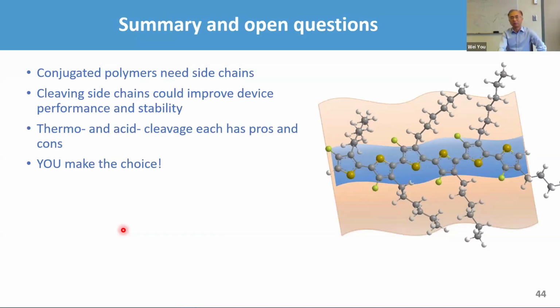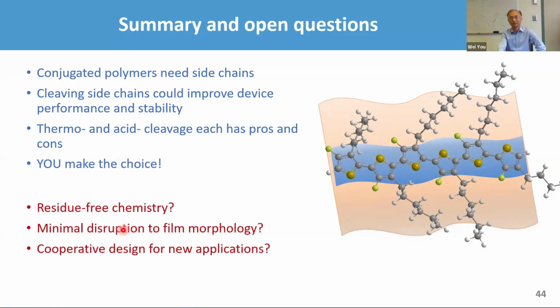So in summary, I hope at this point you understand why conjugated polymer needs side chains. We cannot get rid of that if you want to have the processing. So cleaving side chain will give you improved device performance and stability, right? Because you're being able to increase the Tg, the naked conjugated polymer actually has a very high Tg. So thermal and acid cleavage, each has pros and cons, as well as base and photo, all these things. You make the choice, okay, depending upon your intended application.